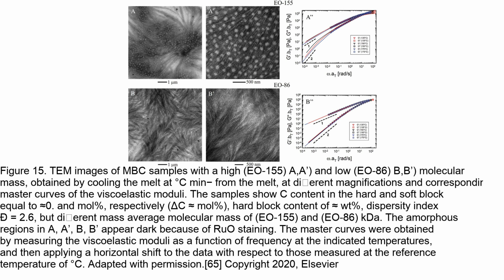The significance of these results is that they provide insights into the solid-state morphology of MBC samples with different chain microstructures and molecular masses. The observed differences in crystal size, number, and arrangement are attributed to the effects of crystallization temperature, melt composition, and the length of the hard and soft blocks. These findings contribute to a better understanding of the structure-property relationships in MBCs and can guide the design of new MBC materials with tailored properties.